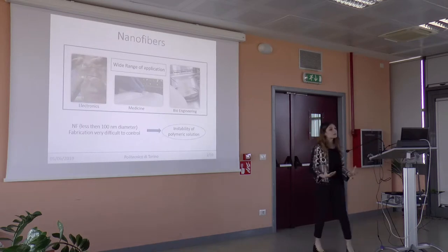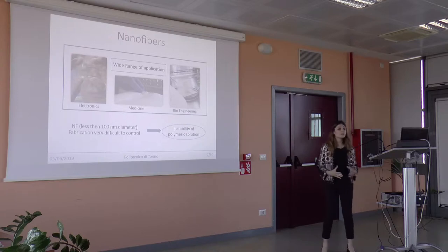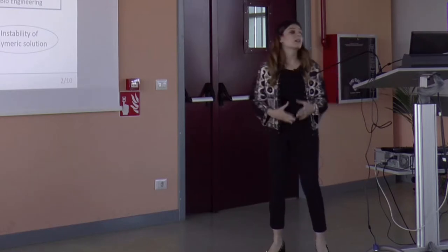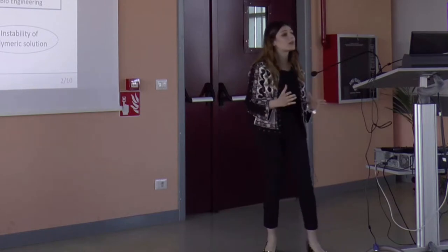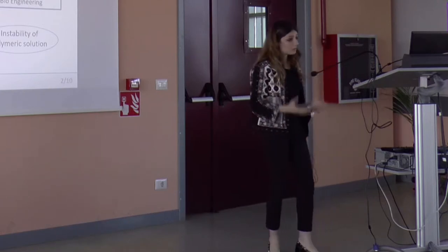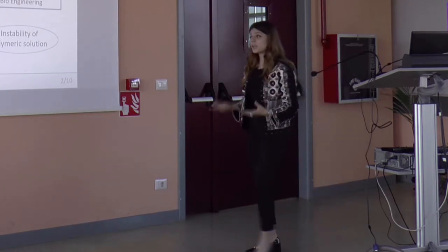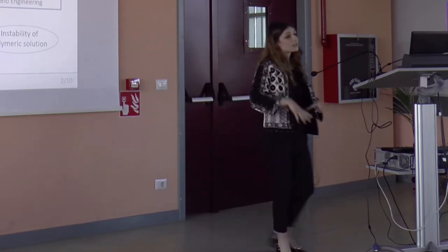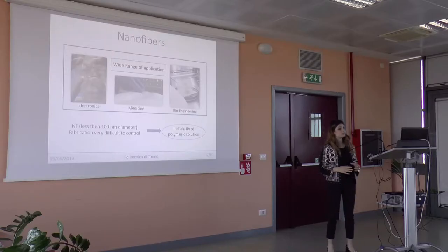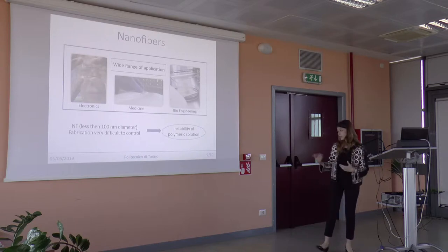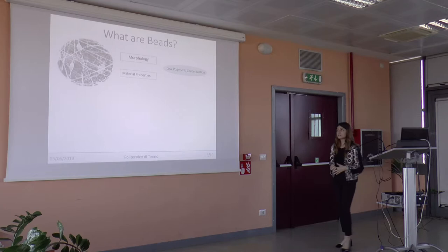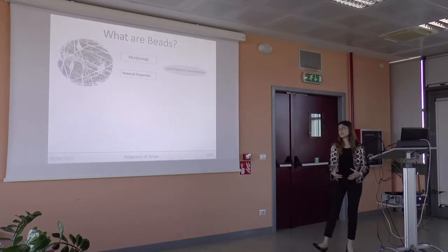Nanofibers have gained large interest in different fields such as electronics, medicine, and bioengineering. What characterizes nanofibers is their small diameter — in fact, they have a diameter less than 100 nanometers. Nanofiber fabrication is very difficult to control because of the instability of the polymeric solution, and in particular the instability of parameters such as viscosity and surface tension. The most common defect of nanofibers is the bead.